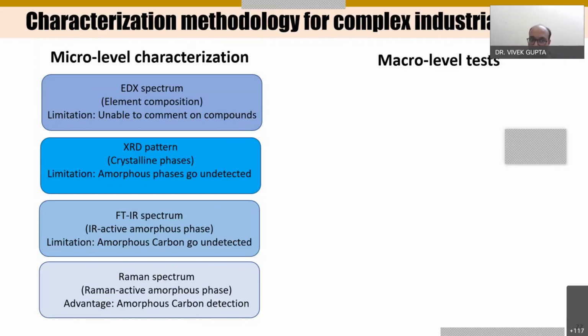Secondly, from the XRD pattern we can detect the crystalline phases very well, but the amorphous phases may go undetected. That is another constraint of XRD patterns. Then we have used the FTIR spectrum: many of the amorphous phases which are IR active we can detect from FTIR, but the amorphous carbon still goes undetected. So for that we have used the Raman spectrum. Its advantage is that the IR inactive phases which are Raman active can be detected as amorphous phases, and additionally we can detect amorphous carbon, whether the LOI is due to amorphous carbon or due to carbonate. That can easily be identified through the Raman spectrum.